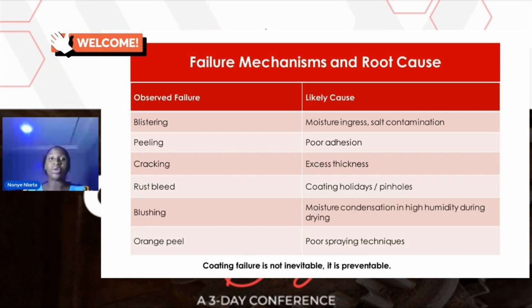So then cracking, which comes from excessive thickness. Then rust bleed. You see a very beautiful coating that you think, oh, this is very nice, very clean, everything looking smooth and shiny, and you start seeing dots here and there with rust from those portions. That is as a result of an area that's been skipped while coating is ongoing. So that's a result of pinholes.